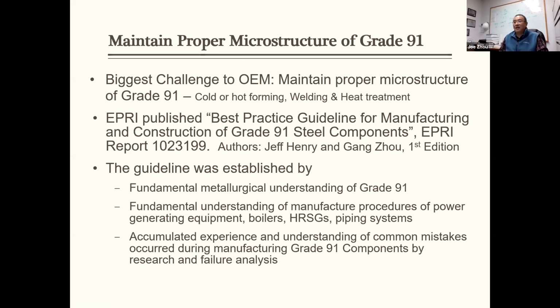That's the reason a lot of people hate to handle T91. The reason is very simple. Among the traditional manufacturing practices used when handling T11 and T22, there are many things you cannot do to the 91, because it has a different microstructure. For example, local torch heating: torch heating T11 is probably okay because its microstructure can tolerate much more uncontrolled heating, but the 91 cannot. If you heat the 91 uncontrolled with a torch, you will likely kill the grade 91.